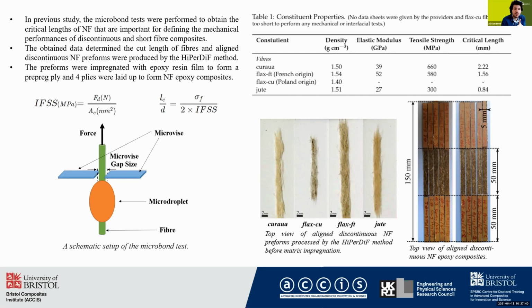The outputs from previous research, which show the interfacial shear strength of fiber with epoxy matrix, obtained by using the microbond test as illustrated in the figure on left, allowed us to calculate the critical fiber length of fibers, which is important to define the mechanical properties of short fiber composites. Thanks to these results, we determined the cut length for this study, and we produced discontinuous natural fiber preforms by using the HiPerDiF method, as seen in the first figure on right.